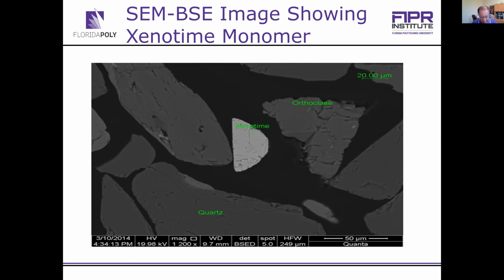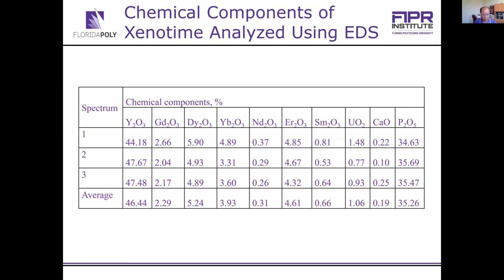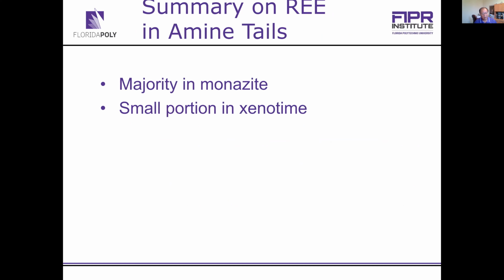SEM image also shows xenotime particles, an yttrium phosphate mineral, in this amine tailings. So we also determined chemical components of this yttrium phosphate compound. It contains various rare earth elements, and particularly yttrium is a major content of this mineral. So in conclusion, based on this research, we found that the majority of the rare earth elements in this flotation tailings exist as monazite and also a small amount as xenotime.